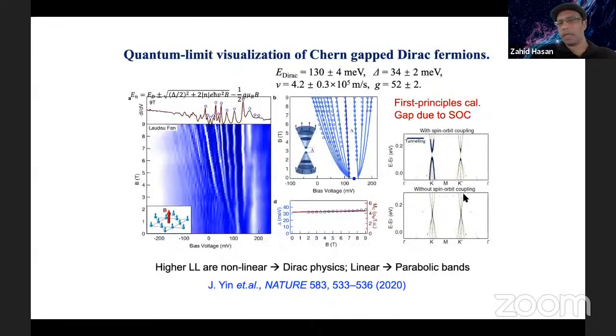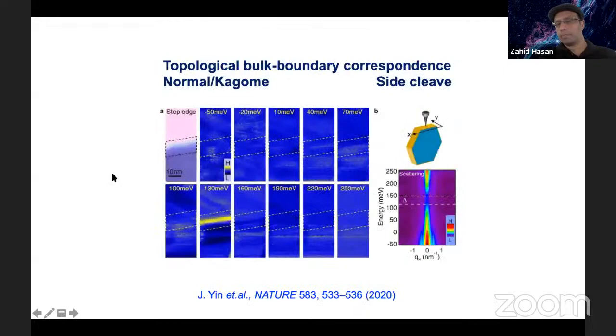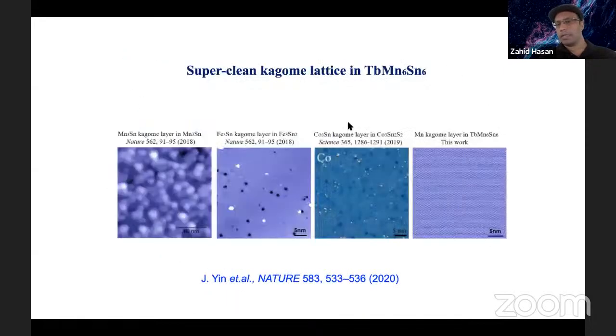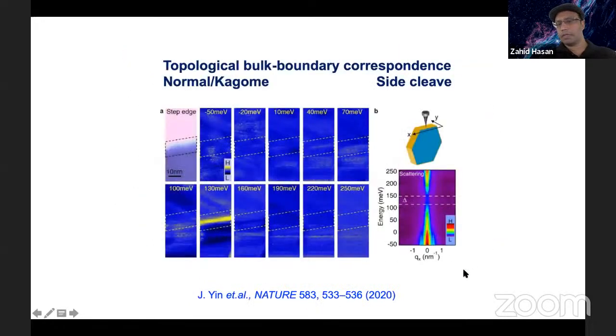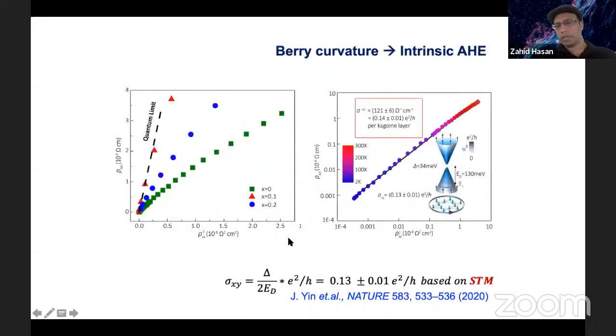And then what is the next step? I showed a drawback: the Dirac point should be at zero, but it's at 130 millivolts, meaning the Fermi level is not here, it's somewhere around here. So we have to tune the material, dope the material to get the Fermi level up here. But when you dope, you are not as clean as this. Then you have dopants, which create some disorder and destroy certain properties. Not all, but still. So this is what I was trying to say: to go to the quantum limit, you have to dope something.